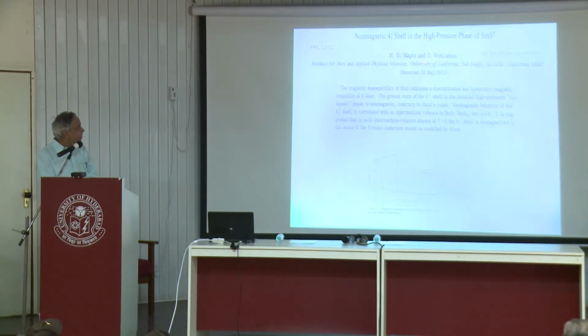They were the first to propose that the 4f electron is hybridized with the conduction band. The net result is that some very unusual state is formed, and that state need not be the same as 2 plus or 3 plus. It gets demagnetized. They proposed that there is a spontaneous movement of the electron from the 4f shell to the conduction band and back to the 4f shell. It keeps fluctuating back and forth as a function of time.